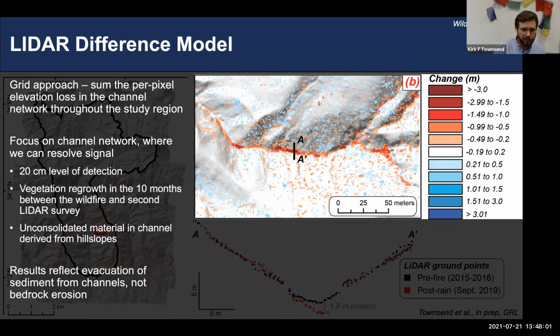And then second, you might notice that there's quite a bit of blue splotchiness on the hill slopes in this map. So that's most likely a consequence of vegetation regrowth. NCALM didn't fly the second survey until 10 months after the fire occurred. And by then, quite a bit of dense vegetative regrowth had already happened on the hill slopes. And then a final point to note is that this signal of elevation loss and erosion likely reflects sediment evacuation from the channels and not actually bedrock incision of the channels.